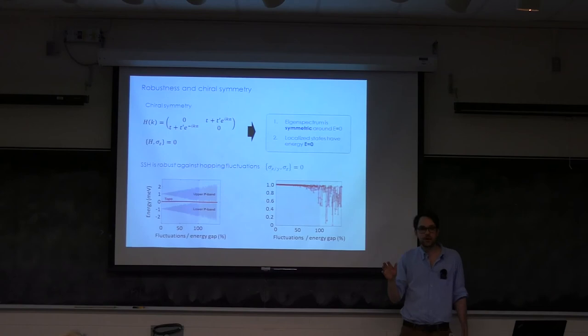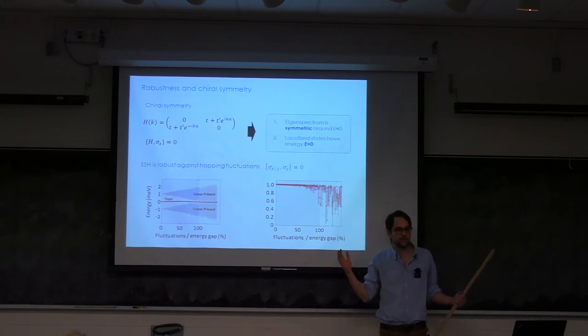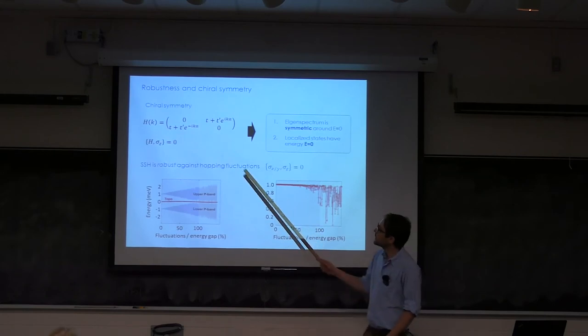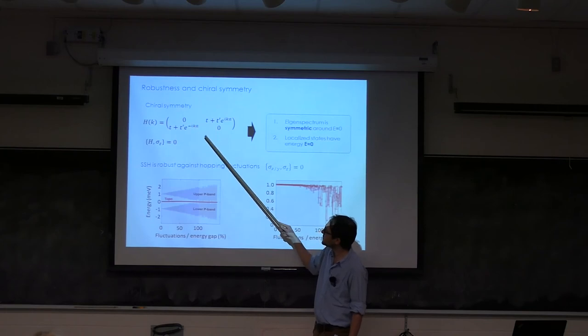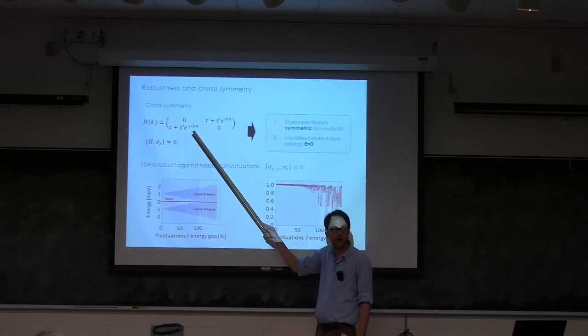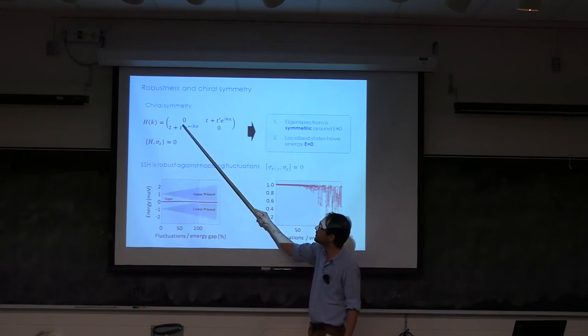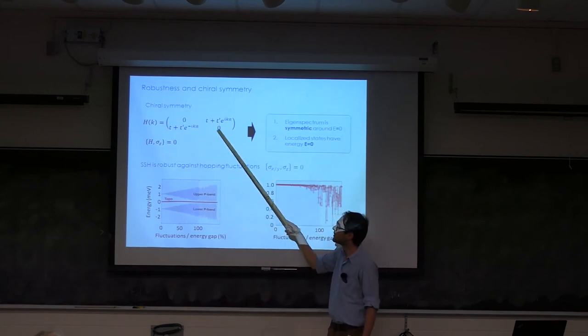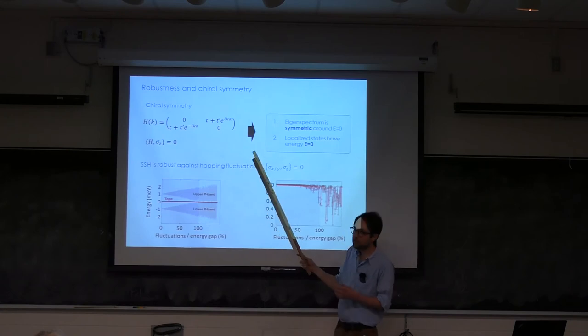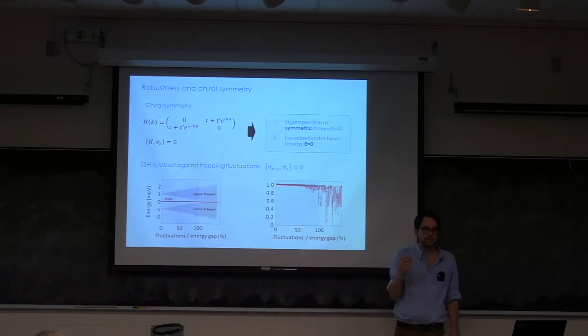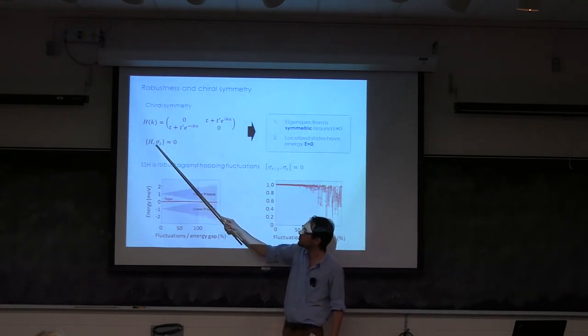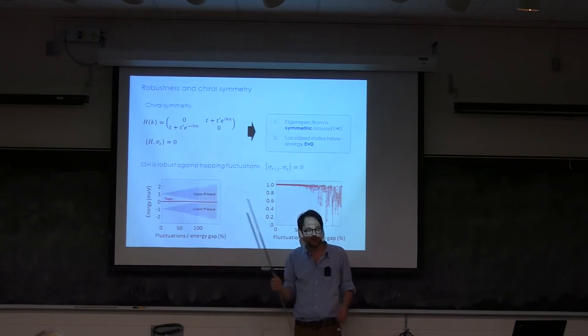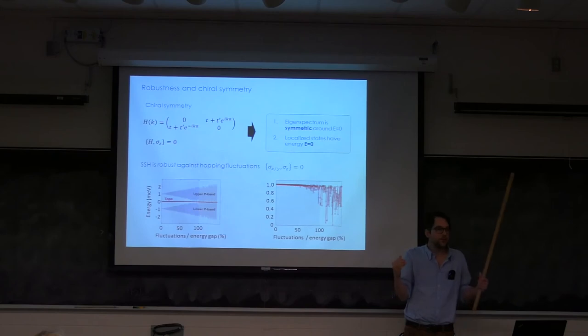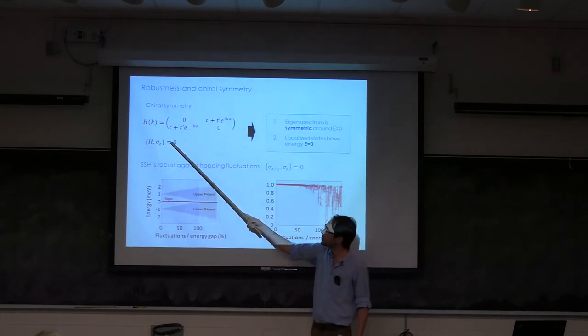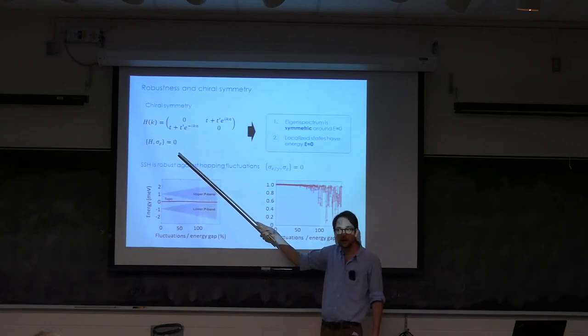Well, I would like to just mention a few words about the robustness of this lasing mode, because that's the entire point of this idea, to explore how resilient it is to perturbation and to start to study this. And so let me take a step back and go back to the Hamiltonian of the SSH model. This is the Hamiltonian in K-space, so we have off-diagonal terms that describe the hopping between the different sites. So a real term for the intra-cell coupling, a complex term for the inter-cell coupling, and zero on the diagonal because all the atoms are identical. And all the topological properties of the system are related to the fact that it carries a really special symmetry. It's called chiral symmetry, the fact that the Hamiltonian anti-commutes with the sigma z Pauli matrix. So this is not as usual. Usually we have a symmetry that commutes with an operator. Here it anti-commutes. And you can show mathematically that the consequences of this anti-commutation rule are really important.